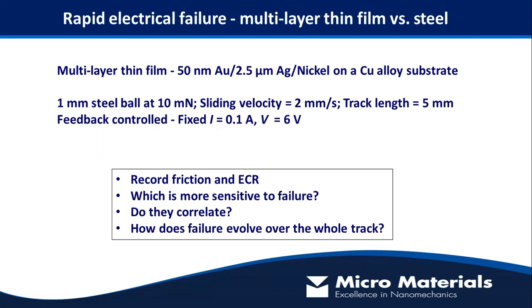So we start off looking initially at a multi-layer thin film stack with a top layer of 50 nanometers of gold, and then there's silver and nickel underneath, and it's on a copper alloy substrate. And we're sliding that against a 1 millimeter steel ball at 10 millinewtons. And we're interested to try and understand which is more sensitive to failure, the friction or the electrical contact resistance, what is the extent of correlation between these two, and how does the failure evolve over the whole track.